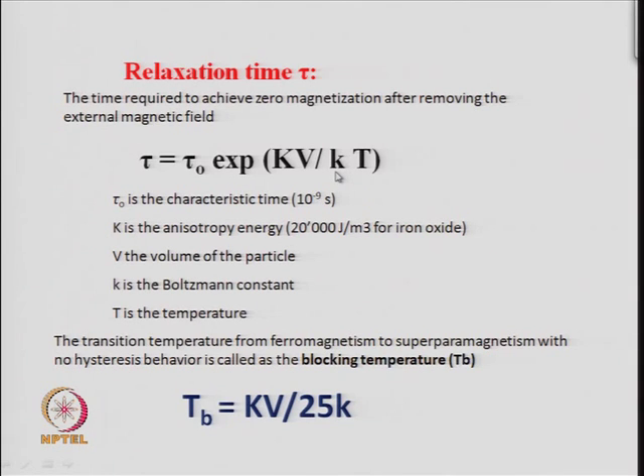The small k here is the Boltzmann constant, and capital K is something to do with the material, called the anisotropy energy, and it changes from material to material. So, for example, if the anisotropy energy is very large, then it will take much more time for the magnetization to decay to 0, because it is exponentially related to the capital K, which is the anisotropy energy. And the anisotropy energy for iron oxide, which is a good magnetic material. So, if you reduce the size of iron oxide particles, make nanoparticles of iron oxide, then you can observe that it will show super paramagnetism, and it will show a relaxation time tau which is related to this equation, where capital K has a value of nearly 20,000 joules per meter cube. There is a value of capital K, and V is the volume of the particle.